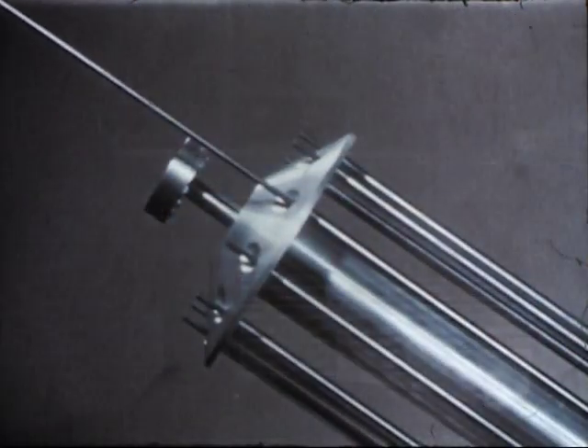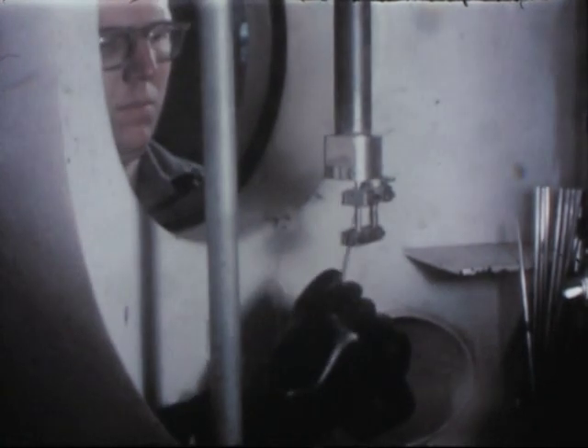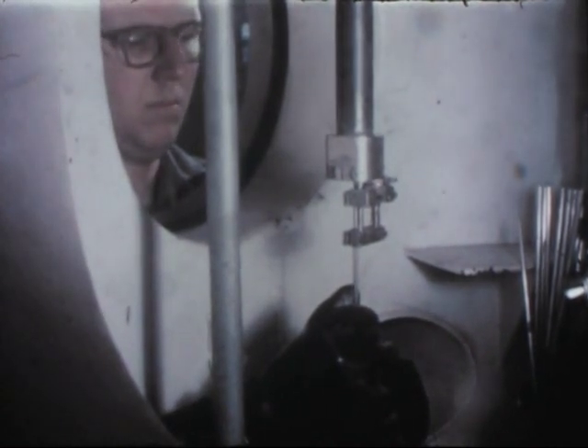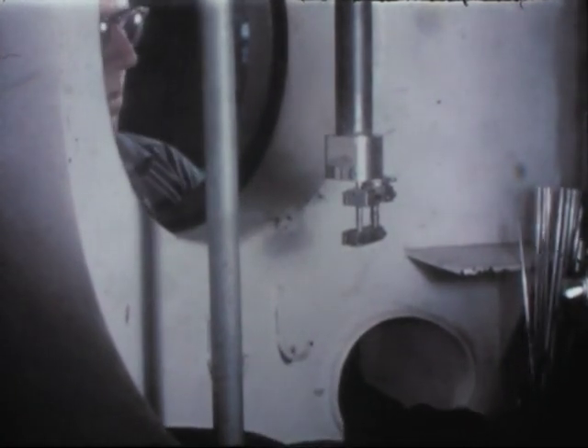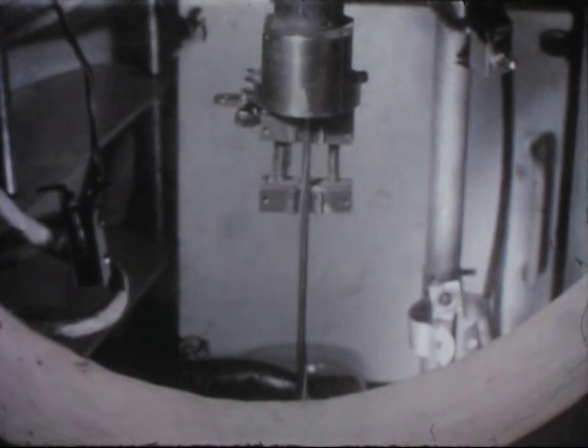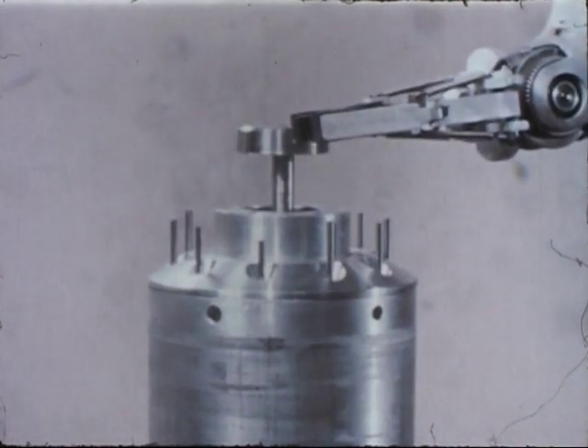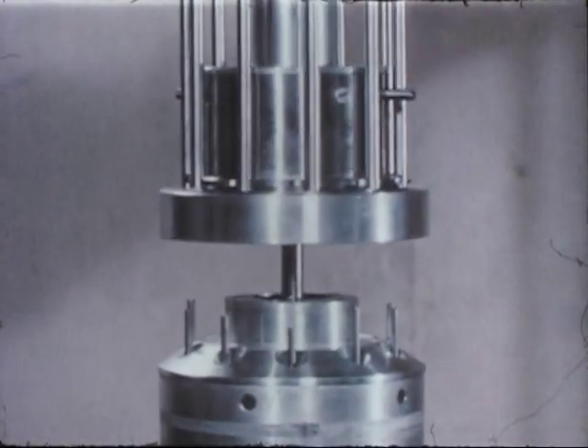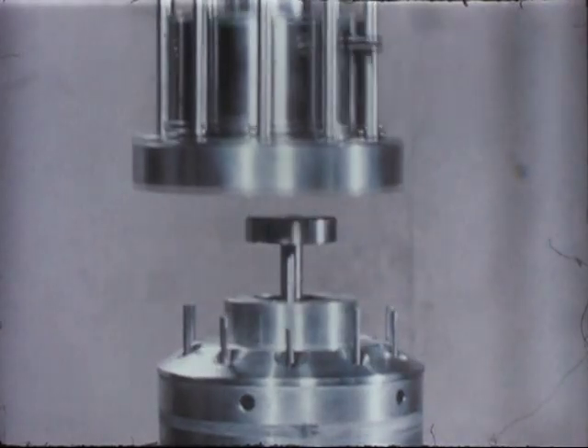The pins in a carrier magazine are transferred to the final phase of the fuel cycle, the reassembly. The initial step, performed in a glove box external to the shielded area, is the charging of an exact amount of sodium to each ribbed stainless steel fuel can. The purpose of this sodium is to fill the six mil annulus which will exist between the fuel pin and fuel can, providing a good heat transfer path and also permitting unrestricted thermal expansion and contraction. The sodium-filled cans are ready for pin loading, and matching of the fuel pin carrier magazine and carrier basket operates a trip mechanism introducing the fuel pins into the sodium-charged tubes.